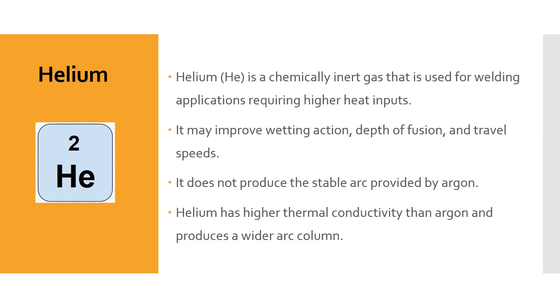Helium — our good friend helium, not just used in balloons at kids' parties. Helium is a chemically inert gas used for welding applications requiring higher heat inputs. It may improve wetting action, depth of fusion, and travel speeds. It does not produce the stable arc provided by argon. Helium has a higher thermal conductivity than argon and produces a wider arc column.